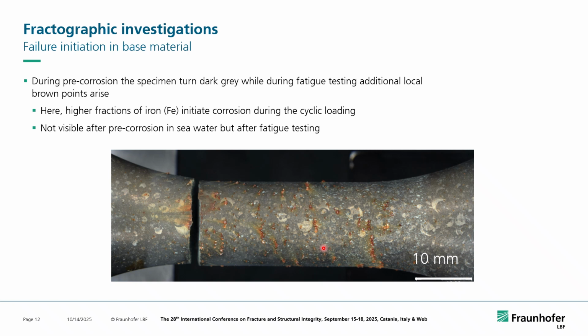Really small quantities of iron. We are talking about, on a nominal level here, around 4 or 5% of iron. Even if we go from 4.1 to 4.15, we have those indications. So it's still in the specification, and the fatigue strength did not change, but we could see that there is